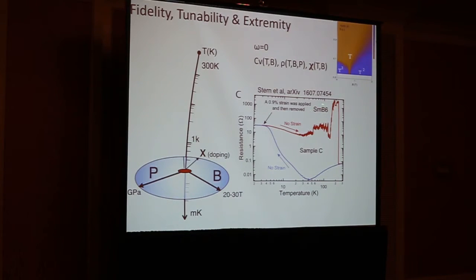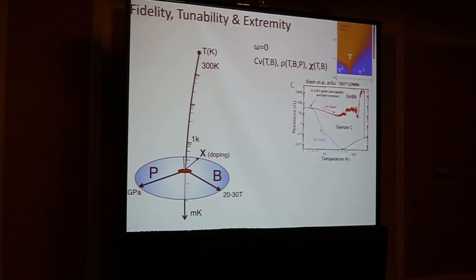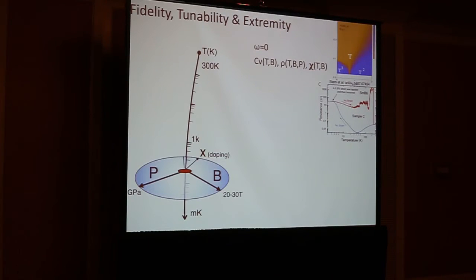In which they take samarium hexaboride and they strain it. And one of the curious things is that when you strain it at low temperatures and then you warm it up with no strain, you see signs that the plateau can actually survive in the presence of strain up to higher temperatures. And this is a matter of great interest. It's as if the characteristic energy scale in samarium hexaboride is increased through the application of shear strain. So here is another example of how, by using extreme conditions, you can get new insight. But of course, what we really like to do is to look at spectroscopy.